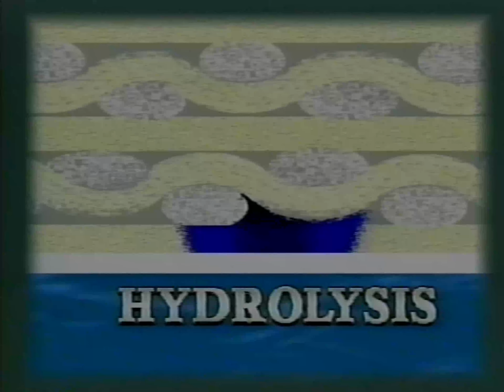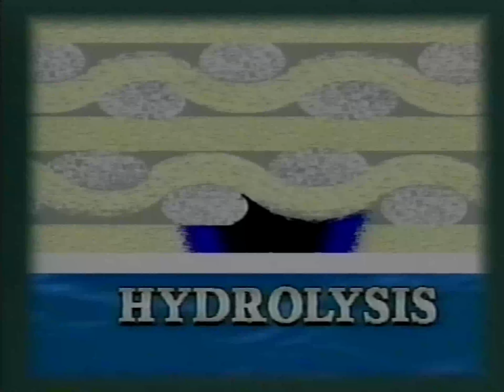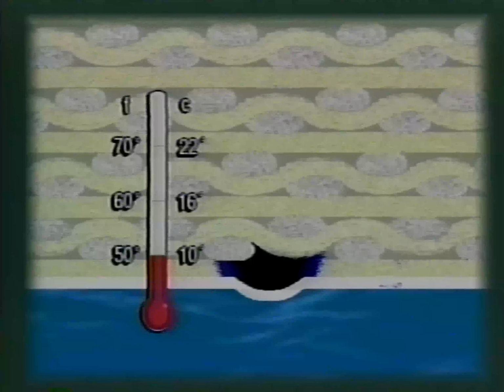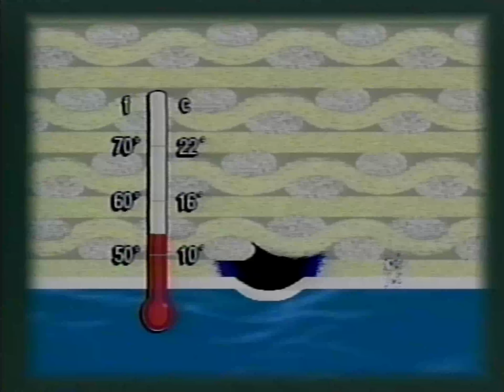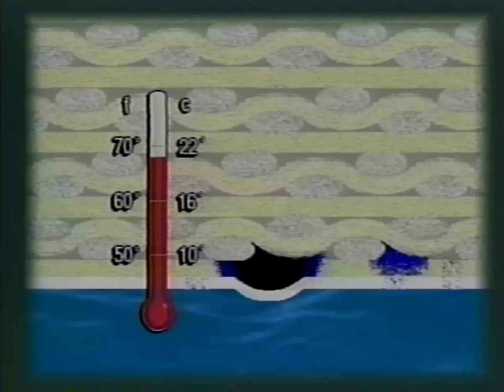The moisture reacts with the water-soluble materials remaining within the laminate from the curing process, and this reaction process is called hydrolysis. The result is a pocket containing acids applying pressure on the Gelcoat surface. Something has to give, so blisters develop. Elevated temperature accelerates this process. So, boats in warm water may experience greater blistering problems than those in cold water. If something isn't done to repair the blister damage and to eliminate the cause, more serious damage can result.